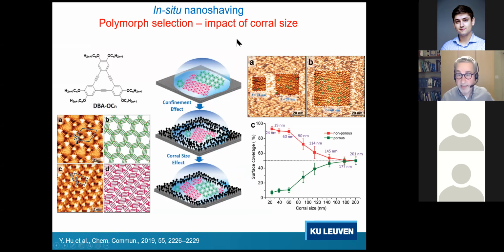So we have now applied this, for instance, for polymorph selection, where we have shown that this is a molecule that can self-assemble into a porous network and into a high density network. We have shown that you can modify the polymorph appearance inside these corrals by playing with the size of the corrals. And in this particular system, the non-porous high density phase is preferentially formed in the smaller corrals, while if you go to the larger corrals, actually the porous phase gets promoted.